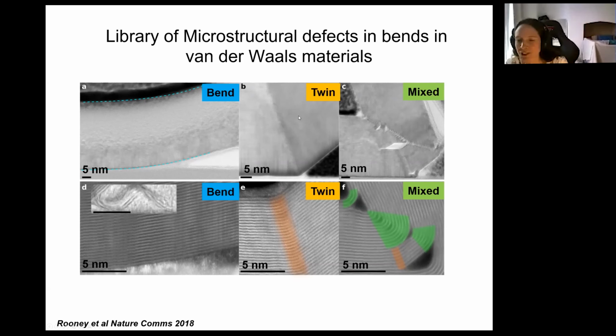And really interestingly, when you start to bend thicker crystals to very large angles, we get this much more complicated pattern, and that's what's shown here. So as you can see here, we've got quite a complicated microstructure, and we can see twins, but we can also see these individual regions labeled in green. So I want to have a little bit more of an investigation of what's going on there.